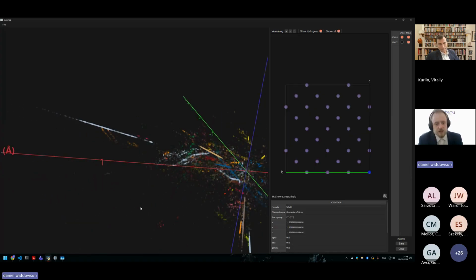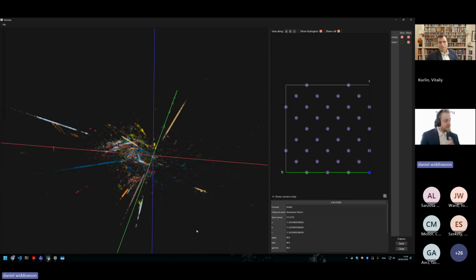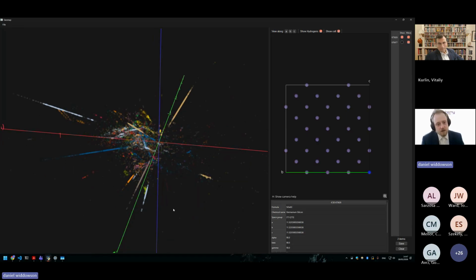Yes, I believe I'll leave that there. What's interesting is if you fly around this, there should be only cubic crystals. I've designated what they are, cubic, and what space group they are. I chose to use PyMatGen's symmetry analyzer with the default settings. That is probably the thing that most people would agree is going to give you the right answer, although some people will disagree. And this is kind of the point, right? If I change those parameters, I'll be labeling some of these crystals as not cubic, or I'll be labeling some other crystals as cubic, and that's a discontinuity.